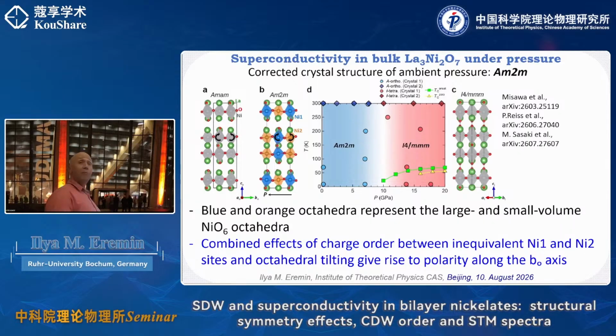So that's very interesting, and I can tell you later that for us it's good news, because we were trying to understand the magnetic and the charge phase in this system, and it turns out that we can largely reproduce the experimental data, except we cannot reproduce the temperature dependence, and I believe that the Am2m phase explains it better.